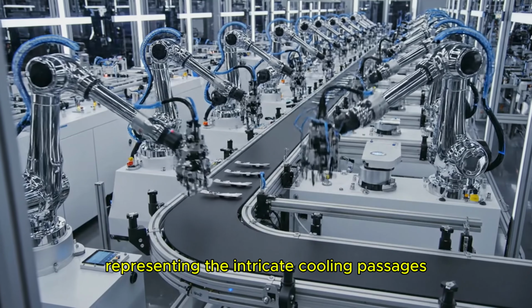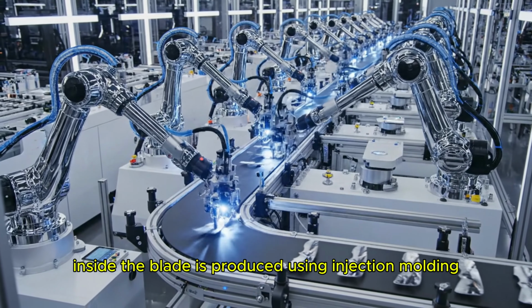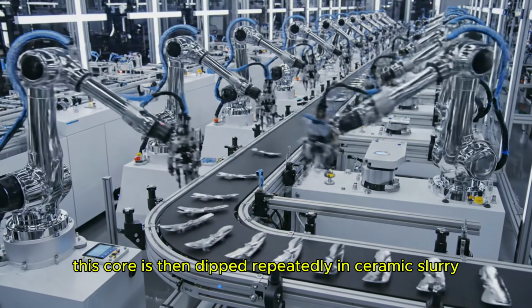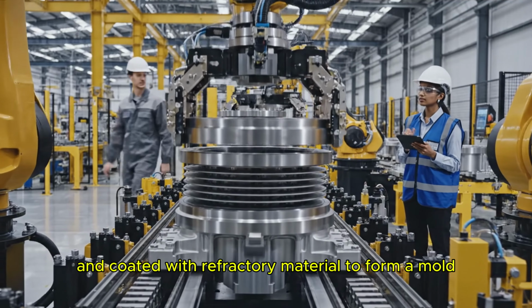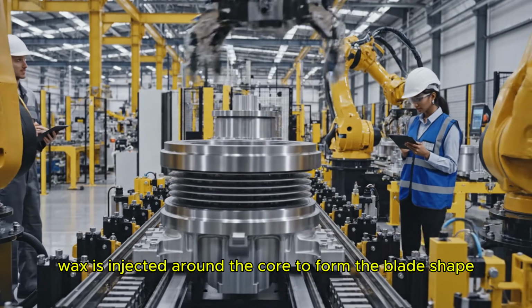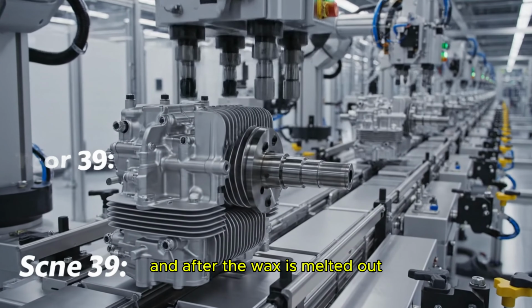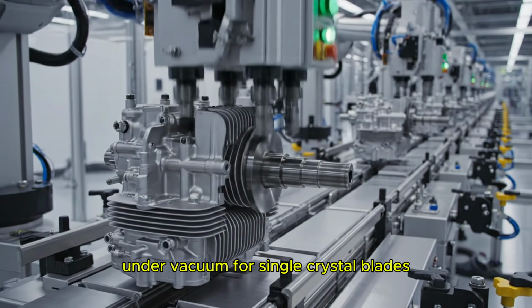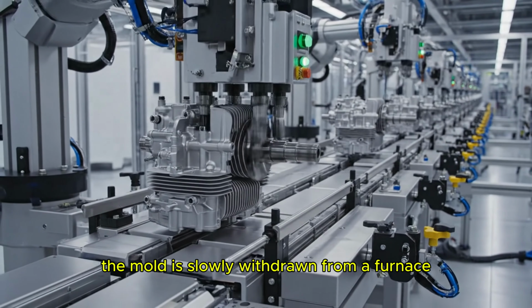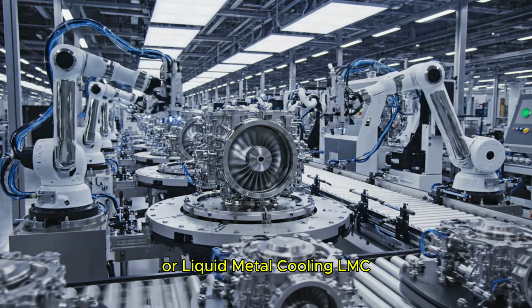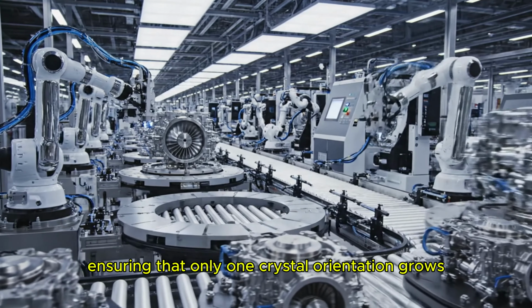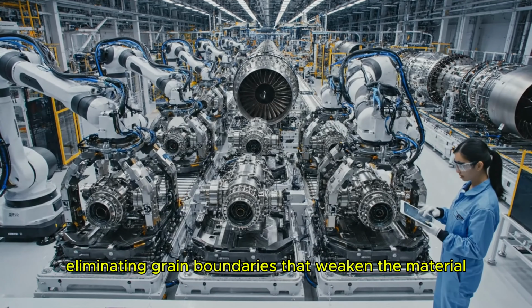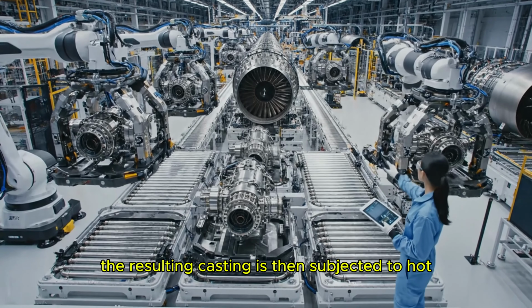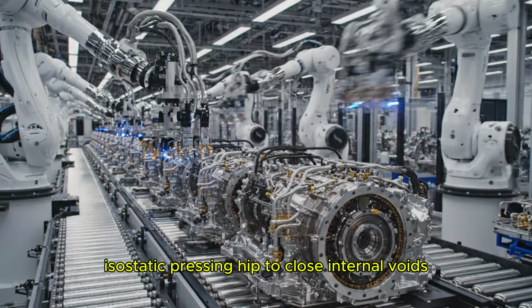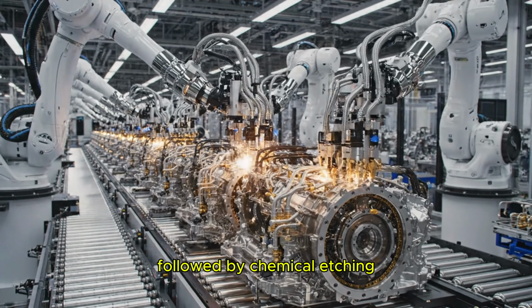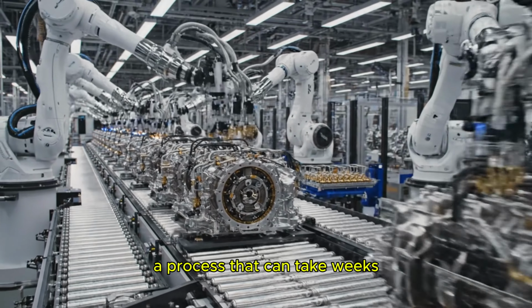A ceramic core representing the intricate cooling passages inside the blade is produced using injection molding. This core is then dipped repeatedly in ceramic slurry and coated with refractory material to form a mold. Wax is injected around the core to form the blade shape, and after the wax is melted out, molten superalloy is poured into the mold under vacuum. For single crystal blades, the mold is slowly withdrawn from a furnace using the Bridgman process or liquid metal cooling, LMC, ensuring that only one crystal orientation grows, eliminating grain boundaries that weaken the material at high temperatures. The resulting casting is then subjected to hot isostatic pressing, HIP, to close internal voids, followed by chemical etching to remove the ceramic core, a process that can take weeks.